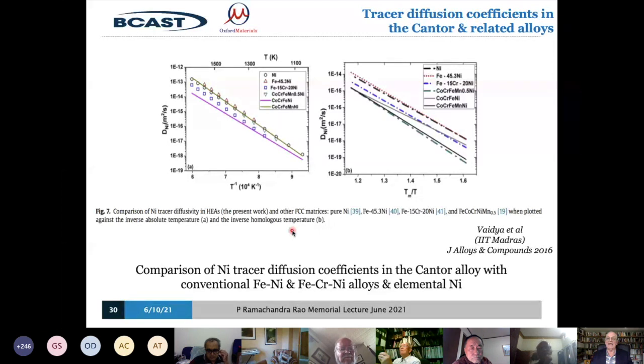For the atoms to move around, I'm not going to go into the details of how it happens for those that aren't material scientists, but they squeeze effectively between the other atoms. They do it by a special mechanism called vacancy diffusion, but we don't need to go into that. They basically have to squeeze through the existing lattice to move. And if you have those local strains everywhere, it's much harder for them to squeeze their way through. In technical language, vacancy motion is constrained. The vacancies get stuck because they're stuck at positions where they're relieving the strain. And this is shown here.